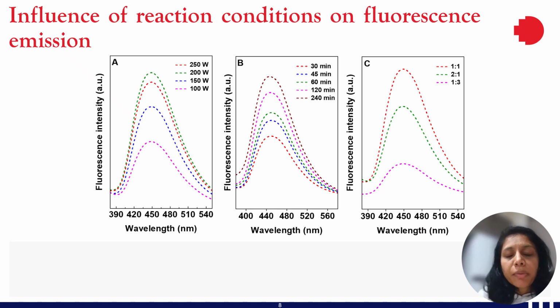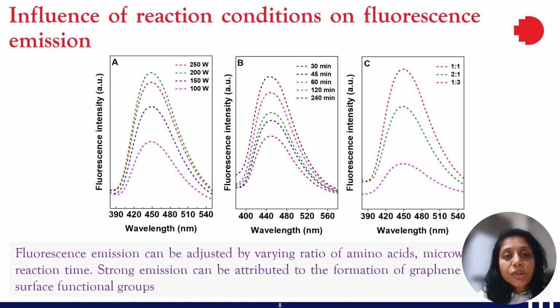However, the emission maxima did not change position when the ratio of amino acids was varied. So these results demonstrate that the fluorescence emissions can be adjusted by varying the ratio of amino acids, microwave power, and time. And the optimized production of these strongly emitting carbon dots is likely attributable to the formation of graphene structures derived from the aromatic group containing tryptophan and surface functional groups contributed by glutamic acid.